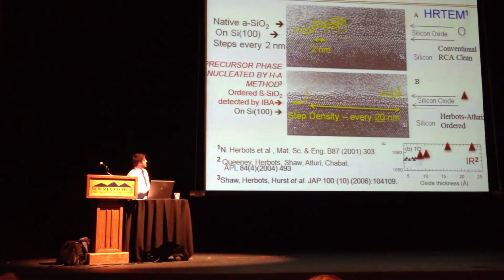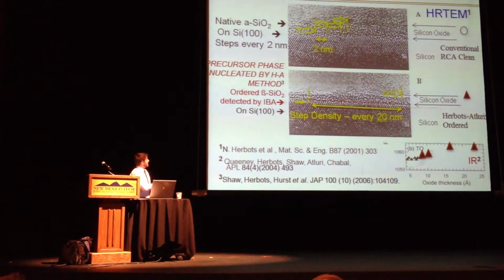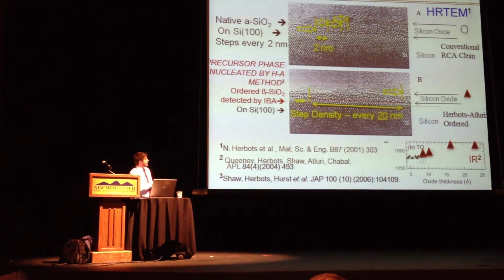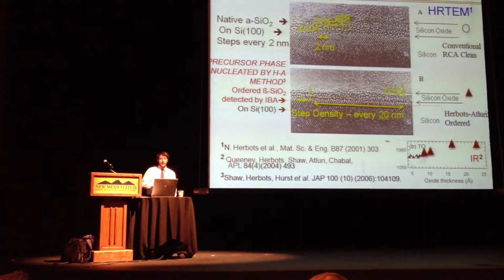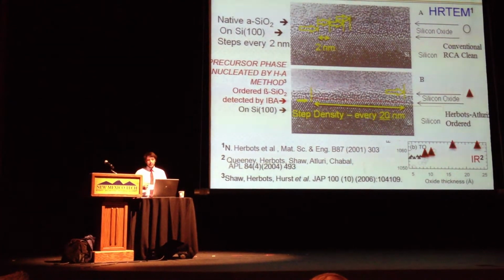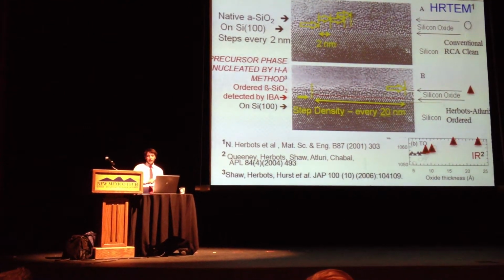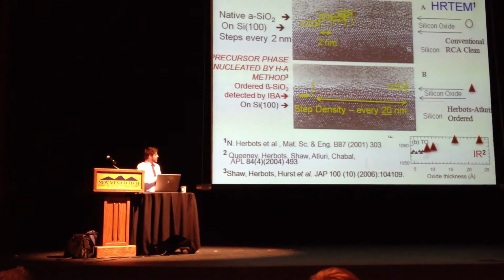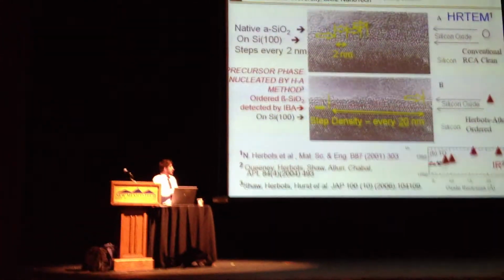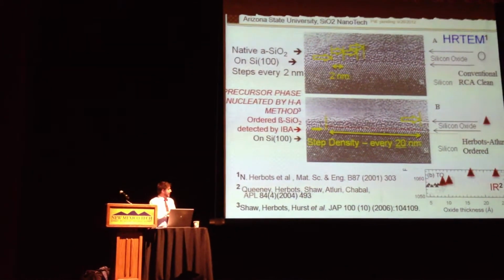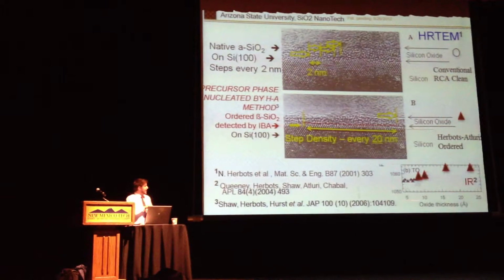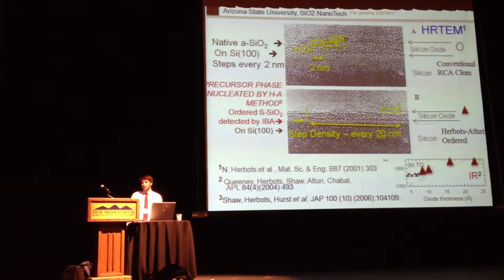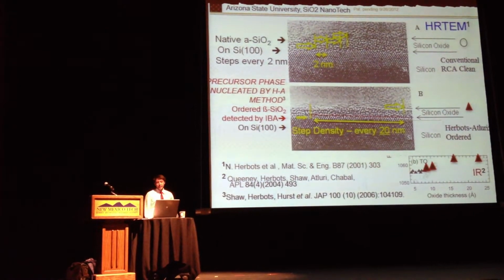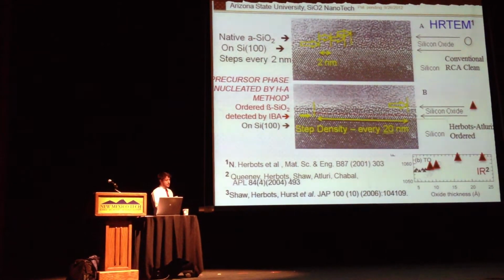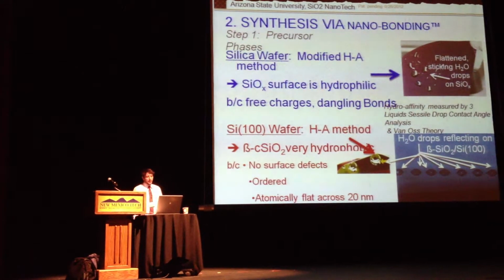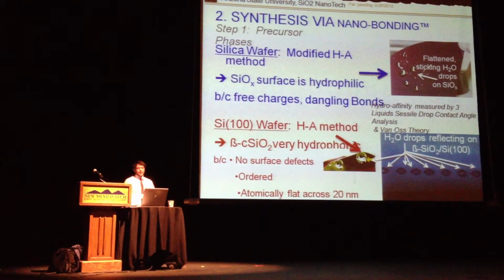And here we have some images of the high-resolution TEM showing a step density of 20 nanometers after our ordering clean, as opposed to 2 nanometers in a native SiO2 on Si-100. Again, some additional evidence here in the infrared. We show that our bond lengths for about 8 angstroms of thickness are relatively uniform, again showing order on the surface.